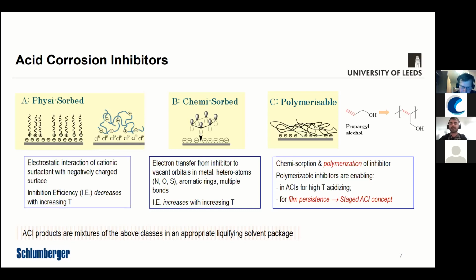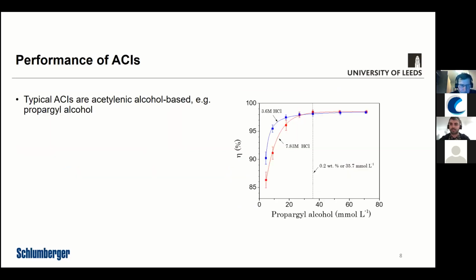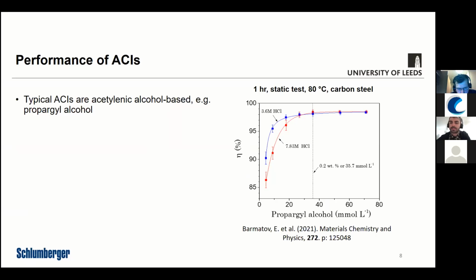So based on the fundamental nature of those inhibitors and how they form a film and how they would polymerize, that is essentially what has led to the development of what Schlumberger are calling the staged approach. But initially, just looking at how the inhibitors perform, just to give you an idea of how effective these inhibitors can be. So this is some measurements of corrosion rates of carbon steel immersed in different strengths of hydrochloric acid with various concentrations of propargyl alcohol at 80 degrees C. And what's plotted here is the inhibition efficiency as a function of these different concentrations.